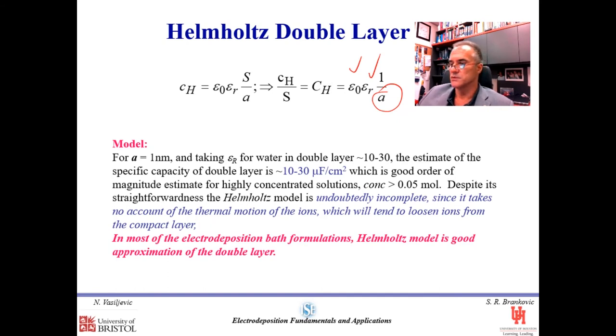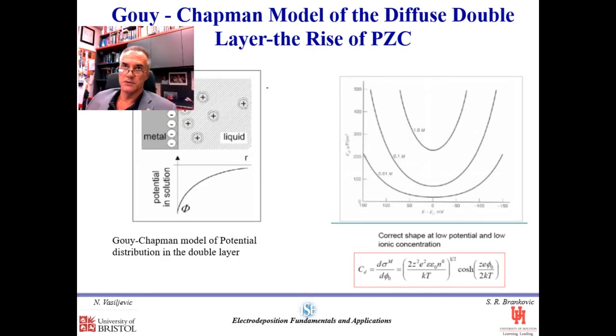For solutions having more than 10 to the minus 2 molar concentration of salts or charged electrolytes, we have a pretty good estimate of the capacity of the double layer, which is very good considering how simplistic this model is. It is a very good approximation of reality. Yet when the concentrations of the electrolyte are very low, 10 to the minus 3, 10 to the minus 4 and so on, the diffuse part of the double layer starts to play an important role. That's the part that is not immediately next to the surface, but is diffused due to thermal motion.